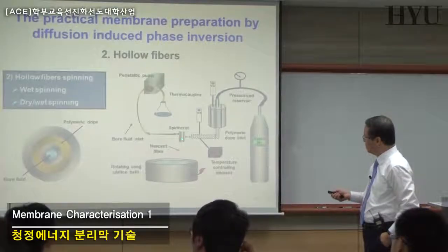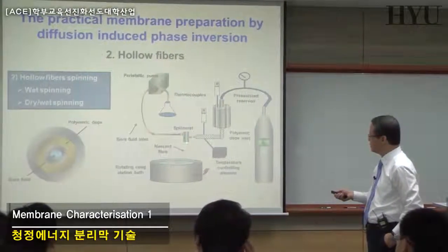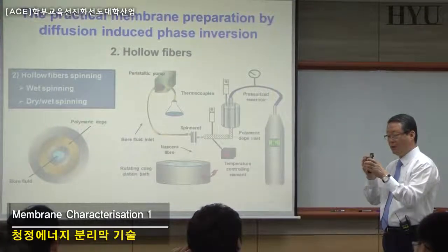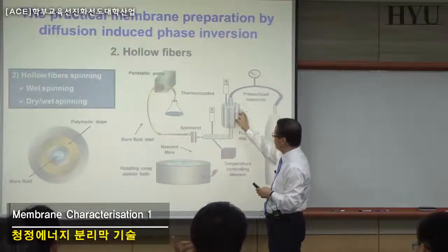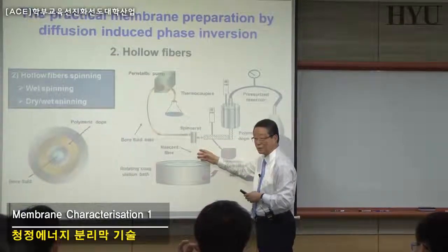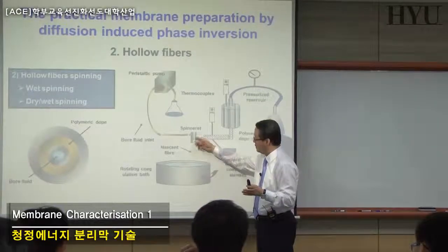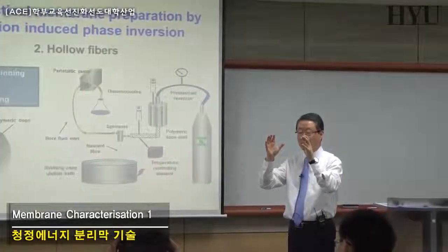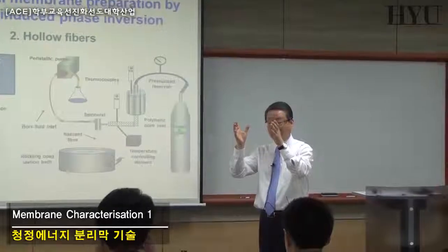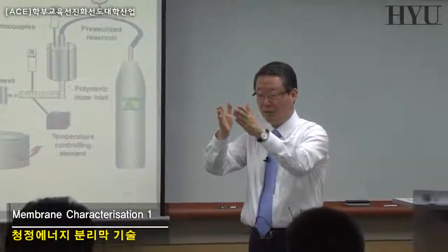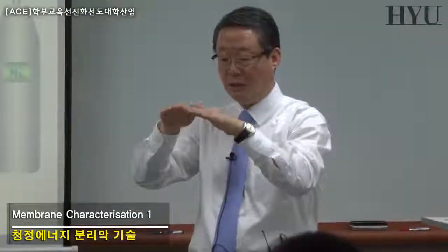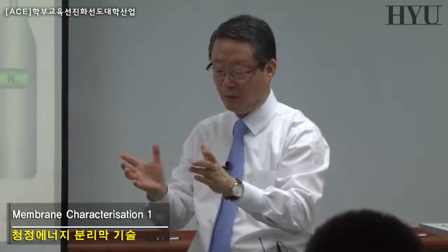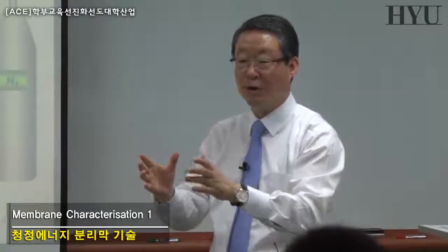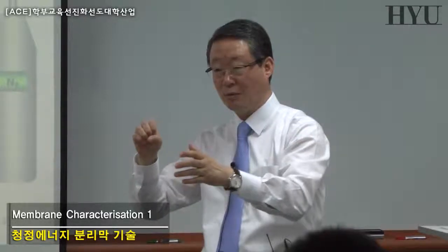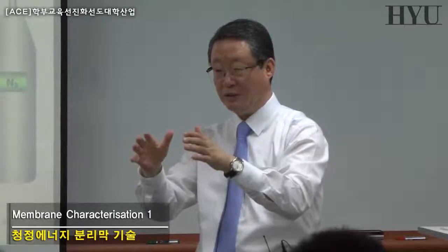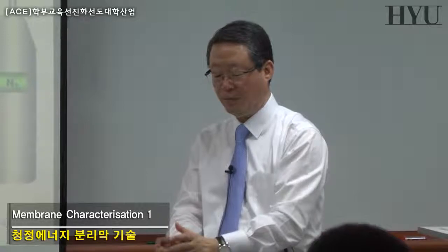Anyway, when the polymer solution exits from the spinneret, the polymer solution was pressurized, so you have a high pressure here, whereas you have a low pressure at atmospheric pressure here. Because of the residual stress applied on the polymer solution inside the spinneret, the polymer solution will swell. Just exiting outside of the spinneret, it is swollen, and then it comes down like this because of the gravitational force and the release of pressure from high to low. You have a die swell just outside of your spinneret, and it's coming down and will be much smaller.